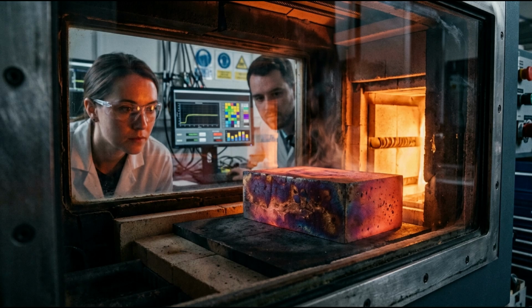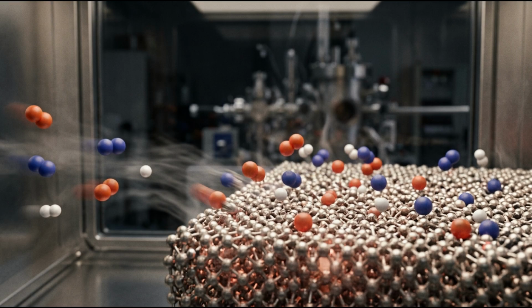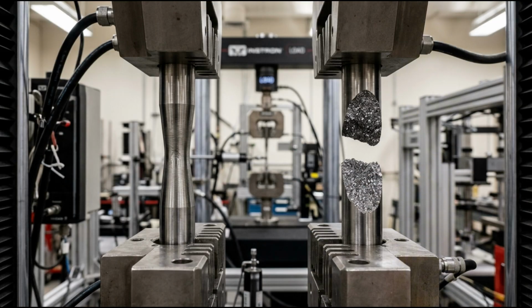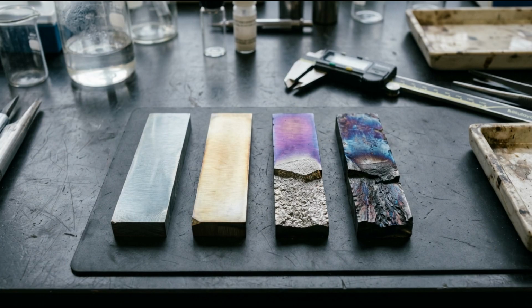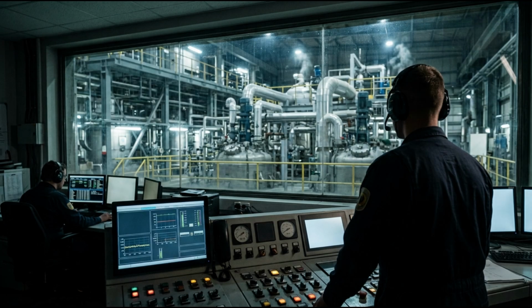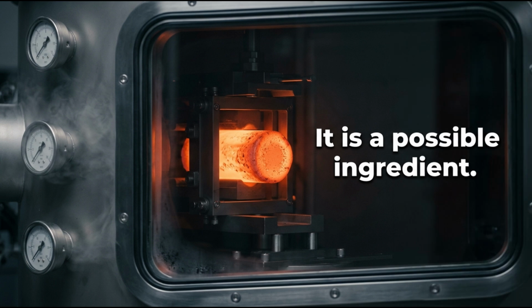Hot titanium can react with oxygen and nitrogen. It can also absorb hydrogen if moisture or hydrogen-bearing materials enter the process. Too much oxygen or nitrogen can reduce ductility. Hydrogen can contribute to embrittlement under certain conditions. The exact effects depend on temperature, concentration, alloy, and processing history. But the factory rule is simple. For hot titanium, the atmosphere is not empty space. It is a possible ingredient.